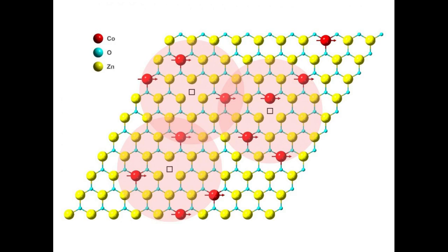Zinc oxide's free electrons could act as an intermediary that ensures the magnetic cobalt atoms in the new 2D device continue pointing in the same direction and thus stay magnetic even when the host, in this case the semiconductor zinc oxide, is a non-magnetic material. The researchers say that the new material, which can be bent into almost any shape without breaking and is 1/1,000,000th the thickness of a single sheet of paper, could help advance the application of spin electronics, or spintronics, a new technology that uses the orientation of an electron's spin rather than its charge to encode data.